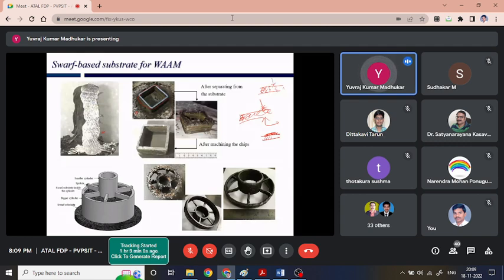So once we are depositing the first layer, in the case of wire arc additive manufacturing, ultimately at the end of the day, we are melting the wire and depositing it onto the base. Now, in the case of a swarf substrate, as soon as we try to deposit on it, what is happening? That molten metal starts flowing in all directions of this porous structure, and we get a structure similar to the roots of a tree. So this shining portion that we could see over here is nothing but molten metal which has flowed in all directions. If I'm looking from the top, this is the molten metal drop which has been formed.